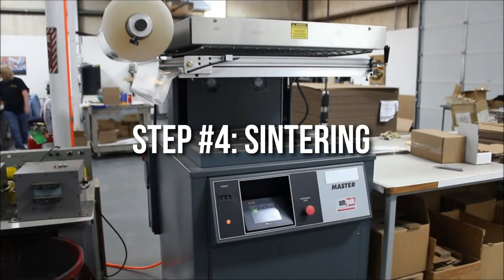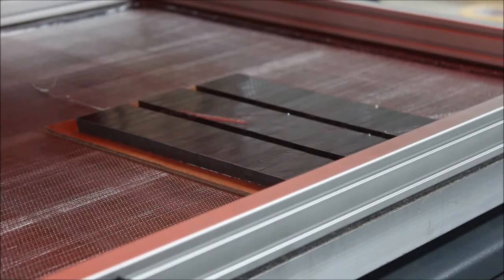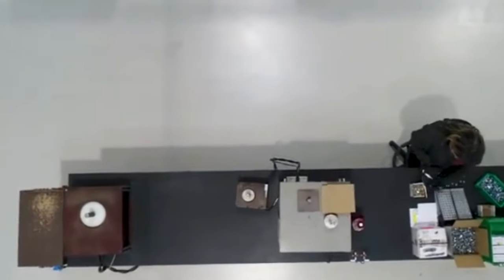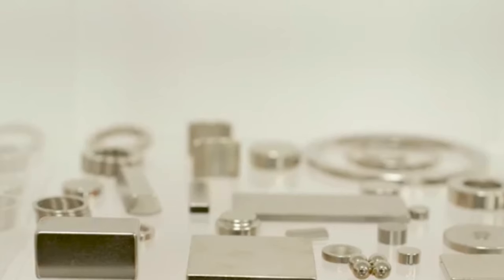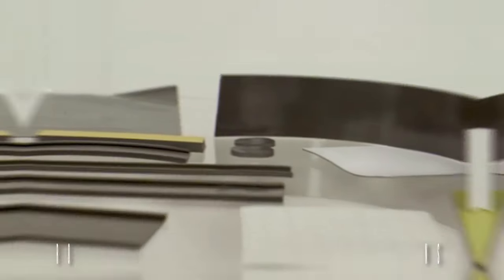Step 4: Sintering. These are directed through a vacuum sintering furnace where the particular temperatures and type of vacuum or inert gas determine the type and grade of magnet being produced. This has a well-studied list of conditions that must be carefully followed. When it reaches room temperature, both materials are given a lower temperature heat treatment. During sintering, the magnets actually reduce in size by about 15 to 20% of their original size, leaving the finished magnets with a rough surface and irregular dimensions.